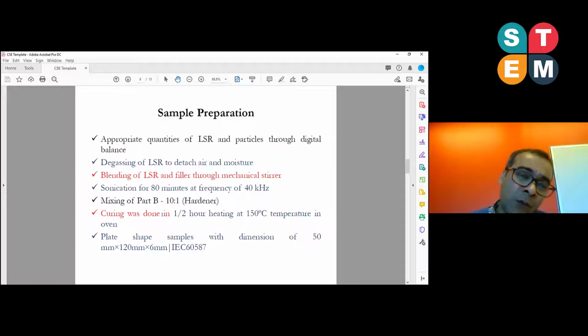Curing was done at a high temperature, 150. After the mixing, all the matrix was poured into the molds, and the molds were placed in a vacuum oven at around 150 degrees for half an hour for the curing. The samples were cured at 50 millimeter by 120 millimeter and 6 millimeter thickness. These samples were chosen according to IEC standard 60587. This standard defines the protocol for how we have to perform the tracking in an erosion experiment.